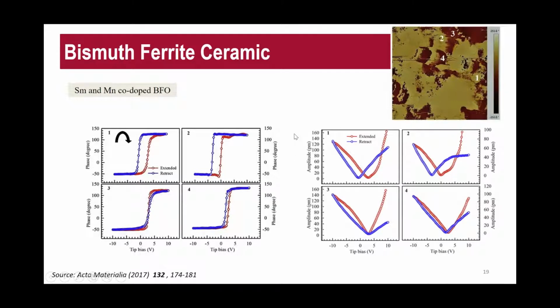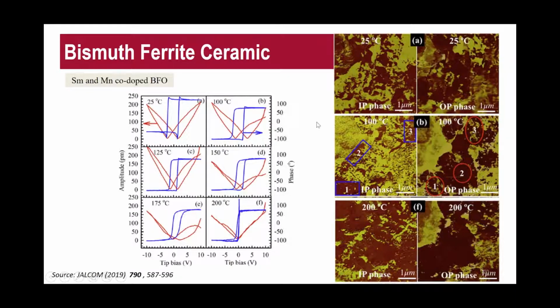We further increase the temperature on the same material, and then we can see the distinct behavior with the change of temperature. So there is a drastic change in the IP. For information, these are all in-plane phase contrast. So in the in-plane phase contrast, judging from here, we can see 175 degrees Celsius is showing a drastic phase transition by the temperature dependent parameters. So this indicates that not only can you understand the in-plane orientation, you can also obtain OOP information from your materials.